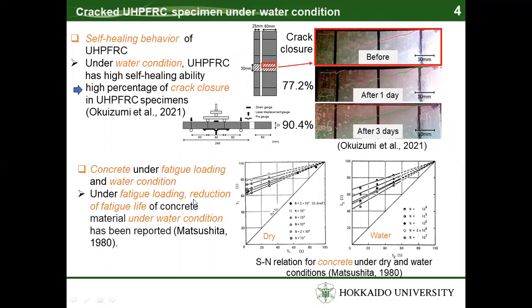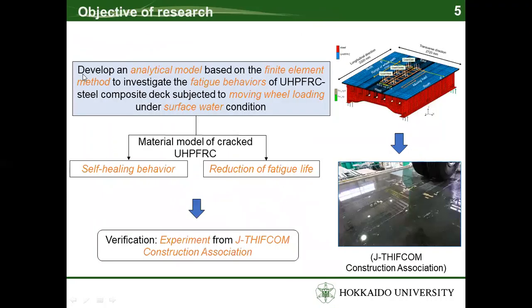However, under fatigue loading, reductions of the fatigue life of concrete material under water conditions have been reported. In this study, the objective of this research is to develop an analytical model based on the finite element method to investigate the fatigue behaviors of UHPFRC-steel composite deck subjected to moving wheel loading under surface water conditions. The self-healing behavior and reductions of the fatigue life are considered in the material model of cracked UHPFRC. The analysis will be verified with the experiment from the J-THIFCOM Construction Association.